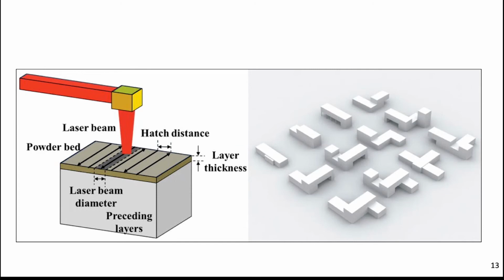So people talk about functional alloys, which are usually based upon the fact that you have different powders. But as I discussed, the technology of feeding powders of different species is not the most attractive, because the ability to control the laser in the process is much lower than in laser powder bed fusion. Here I have a powder bed where I shine the laser. I focus it onto this scan line. And there's a hatch distance and a layer thickness.